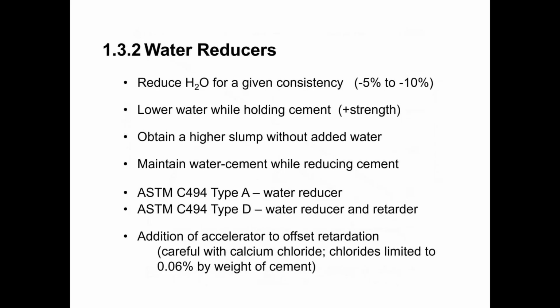All right, next we have water reducers. Water reducers reduce the amount of water that's required for a given consistency from 5 to 10%. So there are a few reasons why we might want to use a water reducer. One is to increase strength. If we reduce the amount of water while keeping our cement content the same, then we are effectively decreasing our water cement ratio, which should give us a higher strength mix. So that's one reason to use a water reducer.